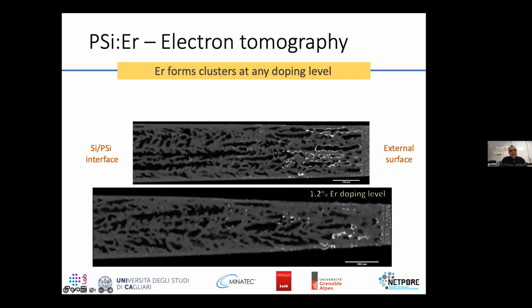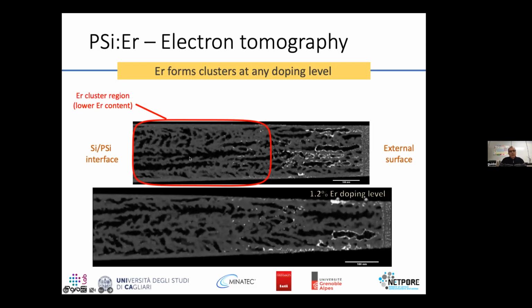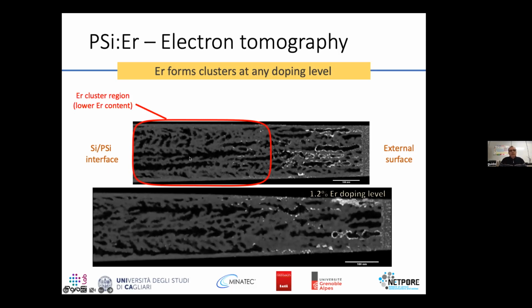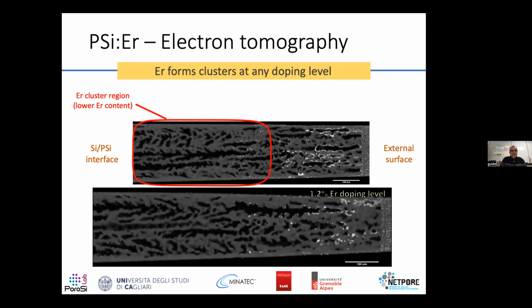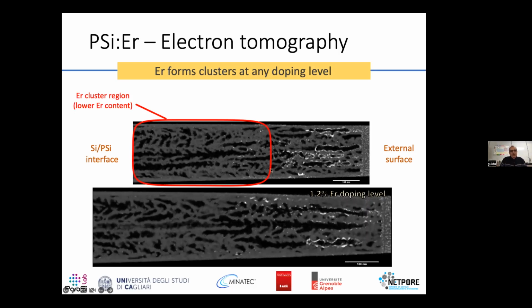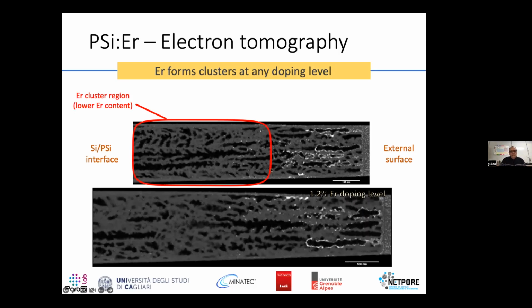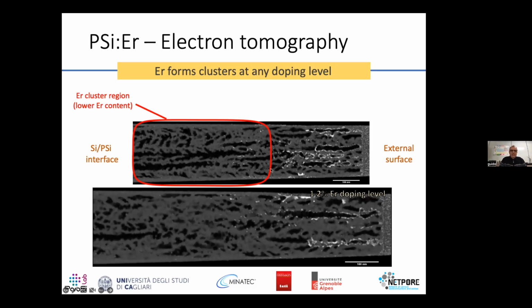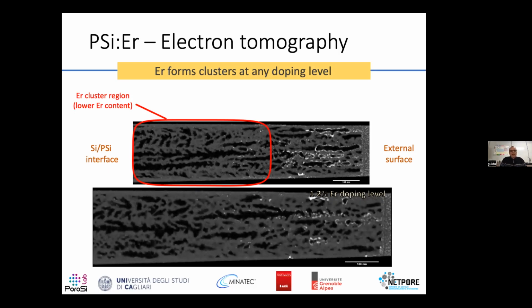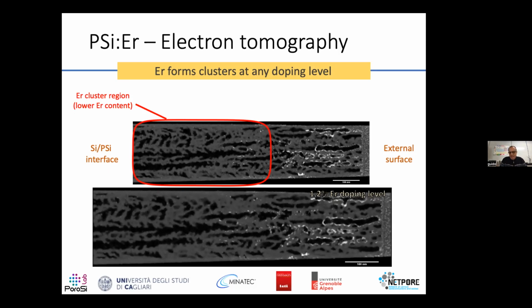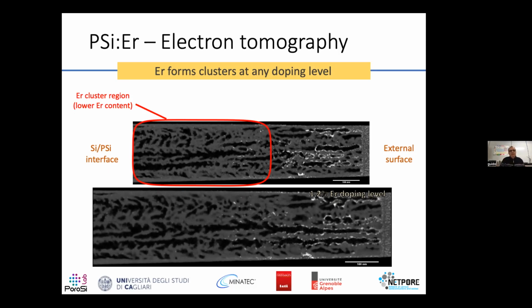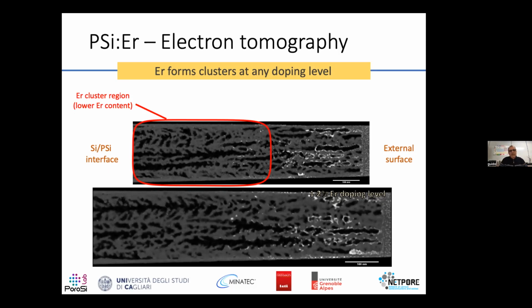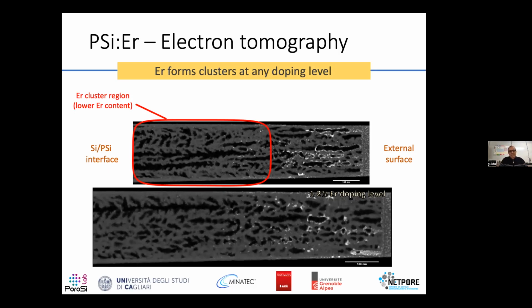But the interesting fact is that here, where you have a lower erbium content, you observe clustering at any depth, so at any erbium concentration. So if erbium forms clusters at any doping level, this means that even if you try to find the better compromise between the content and the light emission, you will still have this clustering problem.